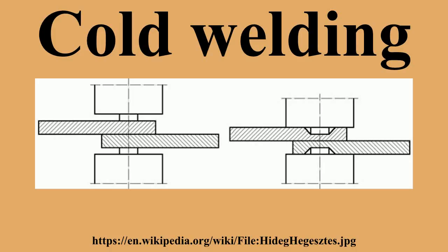Nanoscale. Unlike cold welding process at macro scale, which normally requires large applied pressures, scientists discovered that single crystalline ultra-thin gold nanowires can be cold welded together within seconds by mechanical contact alone, and under remarkably low applied pressures. High-resolution transmission electron microscopy and in-situ measurements reveal that the welds are nearly perfect, with the same crystal orientation, strength and electrical conductivity as the rest of the nanowire.